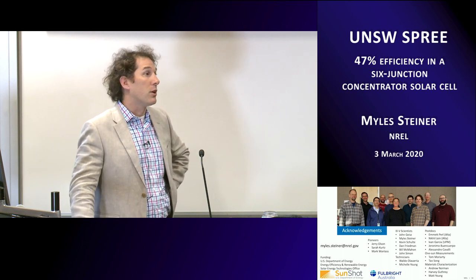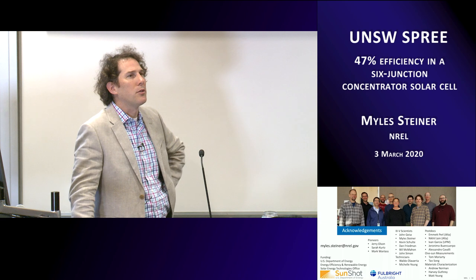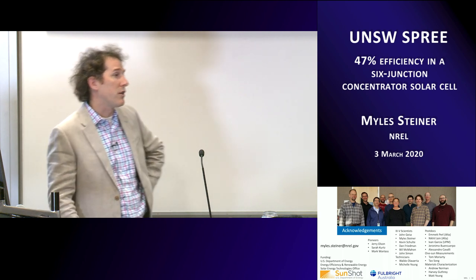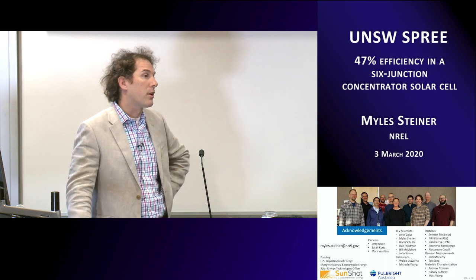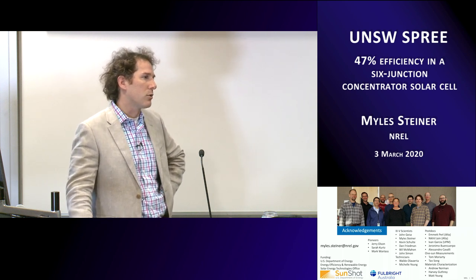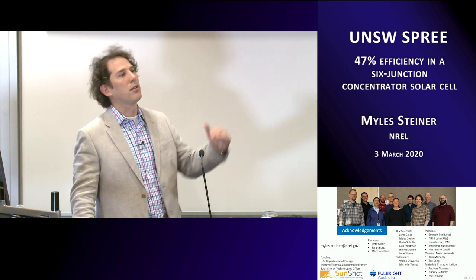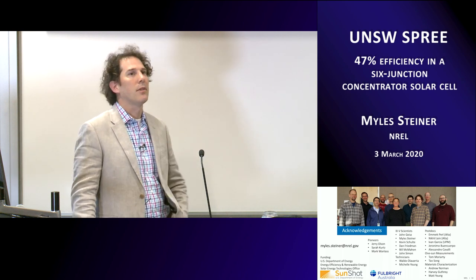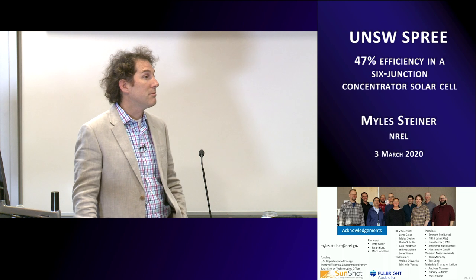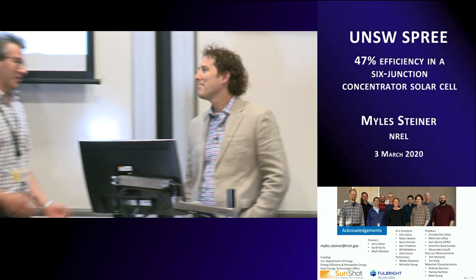You're asking why you have n=2 at all at 1-sun? In silicon you're n=1 down to low current densities. I think the cross-section for Shockley-Read-Hall recombination is just different in the III-Vs, so you get recombination in the depletion region at lower voltages. We see this in basically every cell — at really low intensities you're n=2, until about below 1-sun in gallium arsenide where you've already crossed over into mostly n=1. At higher intensities it stays n=1. I think it has to do with the cross-section for holes and electrons to recombine. Thank you. Well, our time's up — thank you so much for some really amazing results. Congratulations!